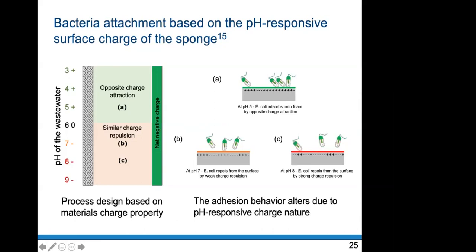So if we take a gram-negative bacteria such as E. coli, what happens is it would attach to surfaces at acidic conditions because of the opposite charge attraction, but it would repel from the surface at neutral and basic pH. As we increase the pH, it would repel further and further. That's what this cartoon here shows. At acidic conditions there will be more attachment, but at neutral and basic conditions, the repulsion increases.